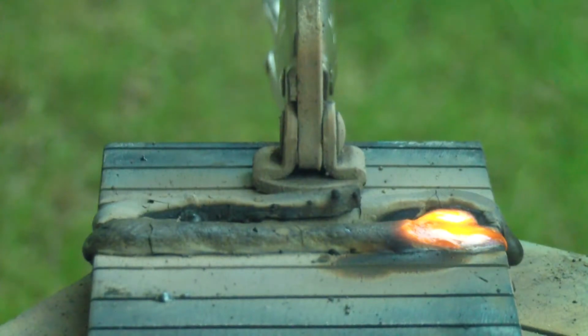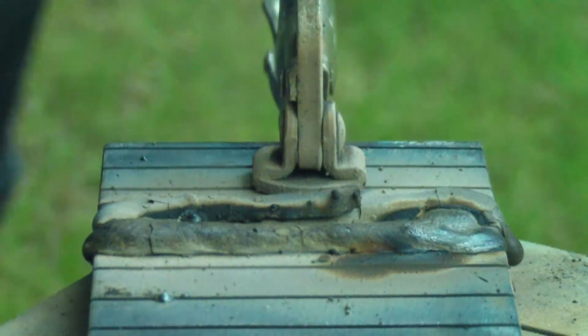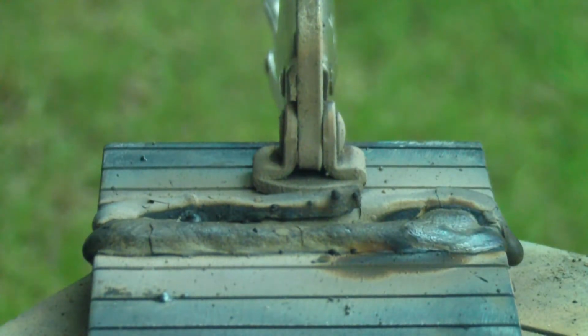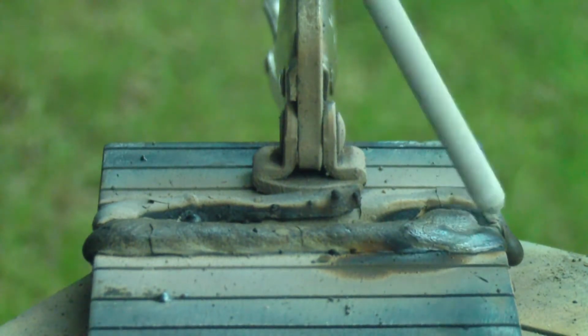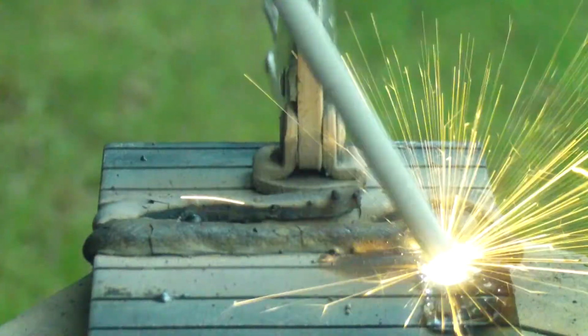The flux will melt slower than the metal core of the welding rod and will form a cup at the end of the welding rod, which shields the arc and helps direct the flow of the molten metal droplets. When the flux melts, it will release shielding gas that covers the arc and prevents the oxygen and nitrogen in the air from mixing with the molten metal, and therefore prevents the formation of oxides and nitrides in the weld, as this will cause a problem and the weld joint will be weak.